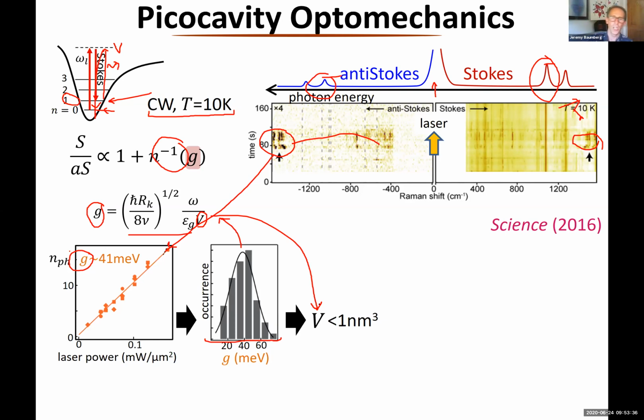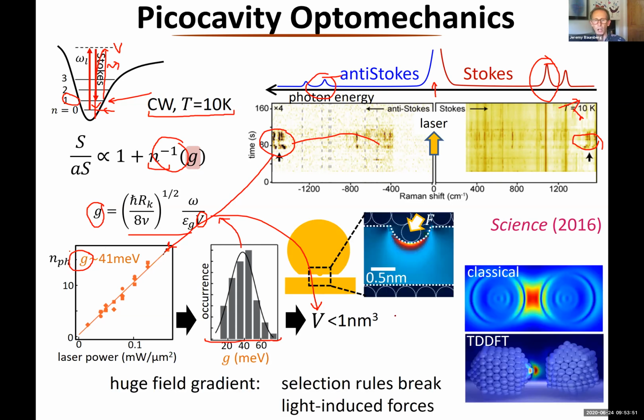The data tells us that if we just take this data at raw value, then indeed what we're doing is we are measuring the occupation of this state. We're vibrationally pumping the system, but extremely efficiently. And that means the optical mode is actually extremely small. And the only way that we can understand that is that it's actually coming from a single gold atom.